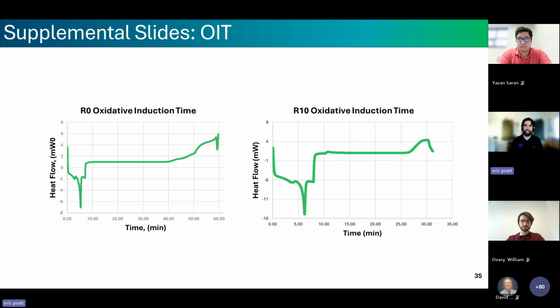After stabilizing, the inert nitrogen gas is switched to oxygen. This marks the start of oxidation. The test continues until an exothermic reaction is visible. This exothermic lift marks the onset of oxidation, and the oxidative induction time is the time from the start of the oxygen to the onset of oxidation.